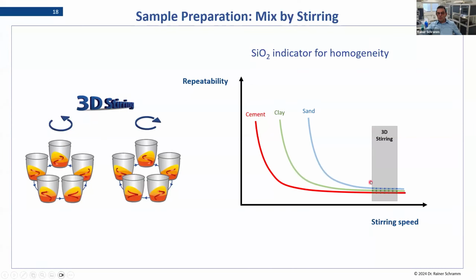And let's explain what this diagram means. It means that, for example, you fuse your sample 3 times, and then you calculate a standard deviation of silicon oxide. And then, for example, if it's a very low standard deviation, a low repeatability error, then you are in a good way. That means your error is very little. But if you then reduce your agitation speed, then there becomes a moment when the error of your 3 repetitions is really increasing, and then you know now it's not working anymore.